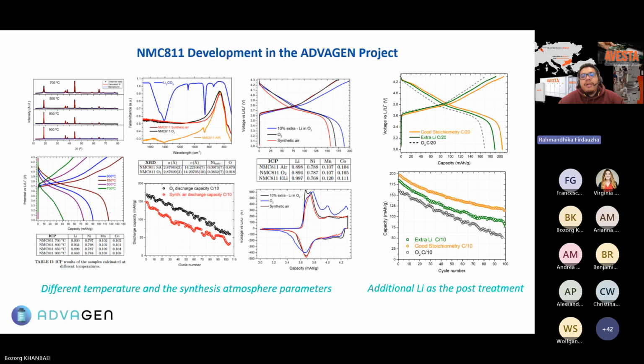So in NMC 811 development in the Advagen project, we approach it with different temperature and synthesis atmosphere parameters. For the different temperatures, we tried parameters like 700, 800, 850, and 900 degrees C, to see the effect on NMC 811 making. We detect by XRD, and then we also check the carbonate appearance by using FTIR. Then we can see NMC 811 with different synthesis atmospheres can show different amounts of carbonate in the end product.